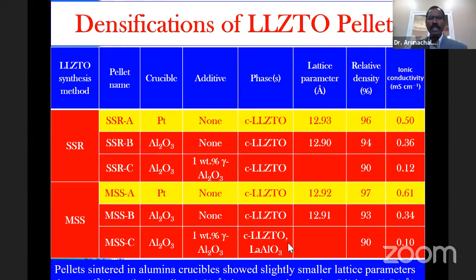But we actually saw it completely off, because with the alumina oxide or γ-Al2O3 as a sintering aid, the density values were lower and the conductivities were also lower. That was mainly due to some grain growth and things like that, or formation of some unwanted impurities like lithium aluminum oxide in the grain boundaries.